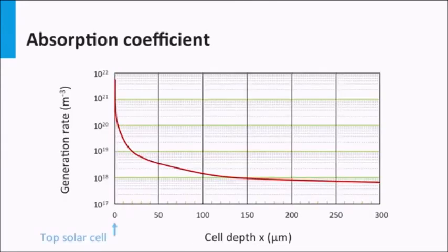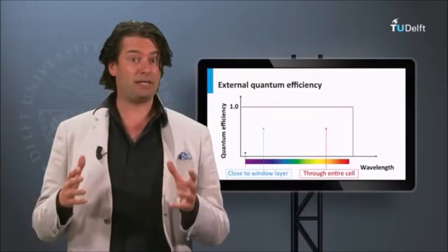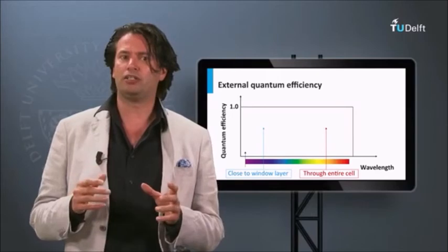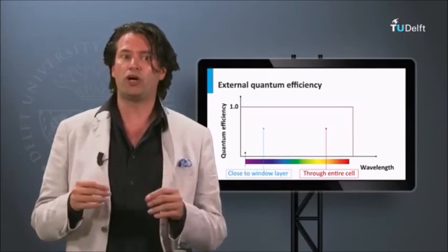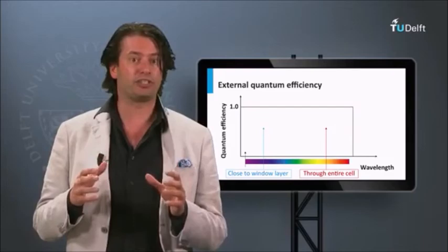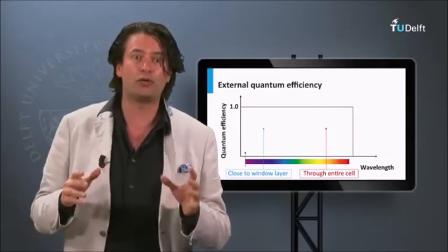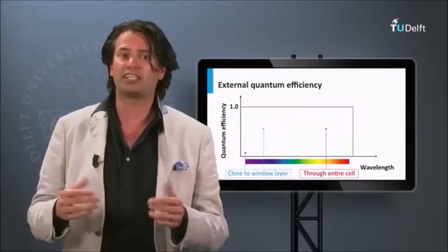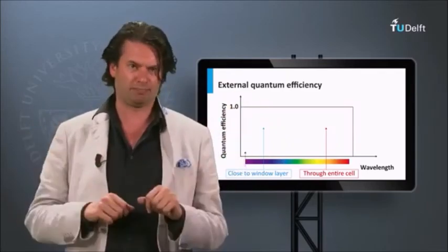As the absorption of photons generates excited charge carriers, the wavelength dependence of the absorption coefficient determines the local generation profile of the charge carriers. At the front side, where the light enters the absorbing film, the generation of charge carriers is significantly higher than at the back side. It means, if we look at the EQE of a solar cell, the EQE values measured in the blue correspond to charge carriers generated close to the window layer, whereas the EQE in the red part represents charge carriers generated through the entire absorber layer.